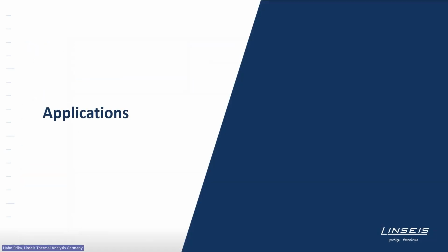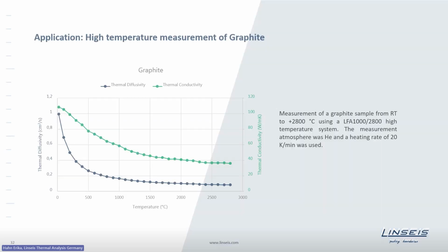To come to an end of the presentation, I just want to show you some applications of measurements performed with the laser flash. A standard one is the measurement of graphite. Here a high temperature system was used where we measured the thermal diffusivity of graphite up to 2800 degrees Celsius with many temperature steps in between. So that is a very classical example of measurements.